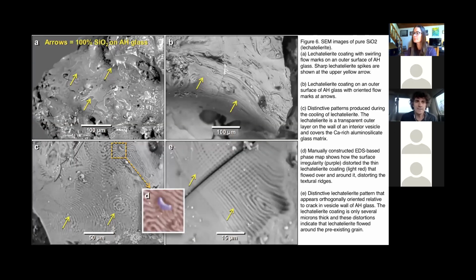Look at this example. Look at that Lechatelierite. If you've never seen it, it's beautiful. You can see the glassy textures, and you can see these even pointed surfaces of Lechatelierite, which is quite unusual, indicating again a very high temperature. And here, the Lechatelierite is blanketing these flow marks, which means that this material was in motion at the time of deposition. When you look a little closer, the Lechatelierite has a very interesting morphology, with this repetitive pattern. And sometimes you can see a disturbance of this pattern because of the material underneath, which, for example, had a different thermal conductivity.